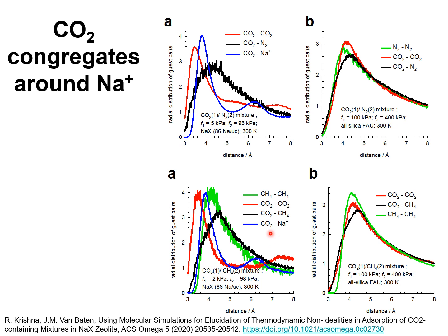Introduction of extra framework cations leads to congregation of CO2 around those cations, and for both these mixtures, the partner molecules, nitrogen in this case and methane in this case, have to incur less severe competition with CO2 for mixture adsorption.